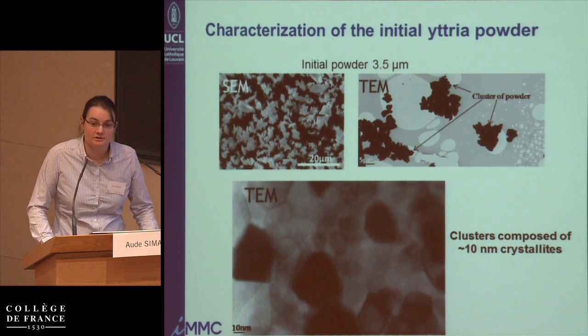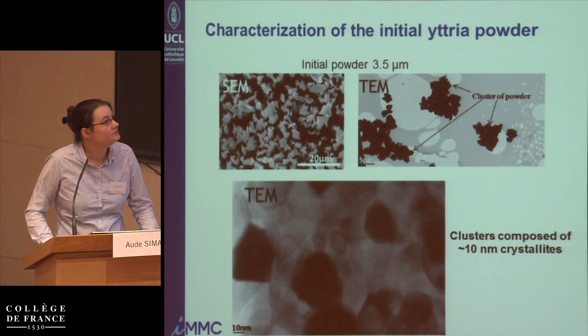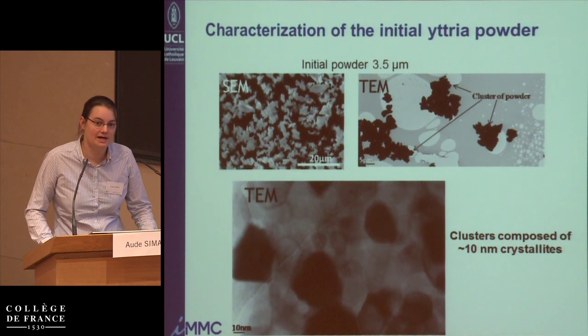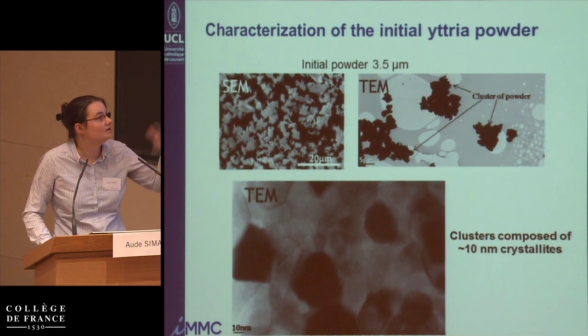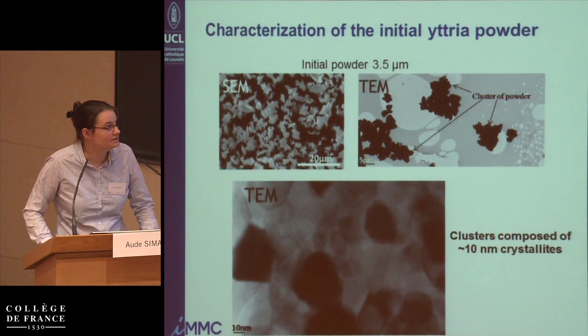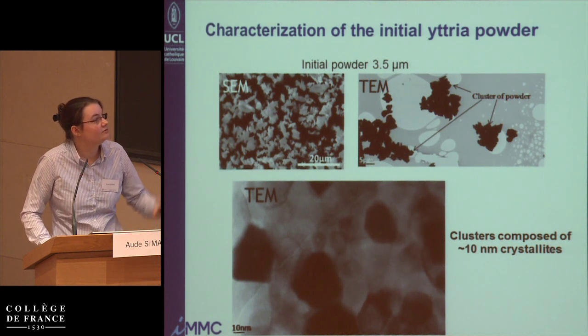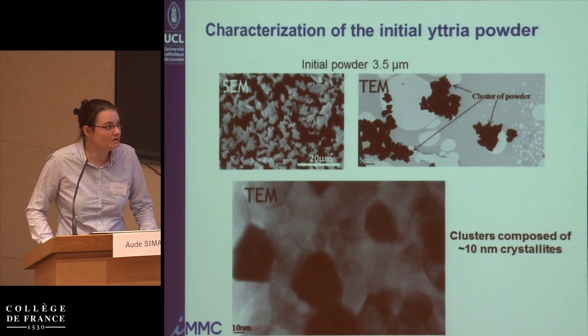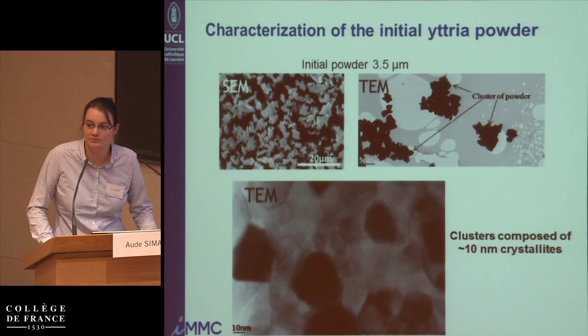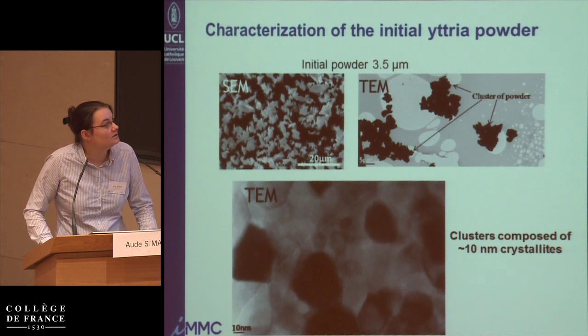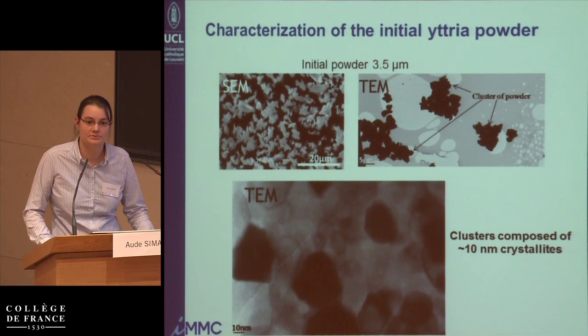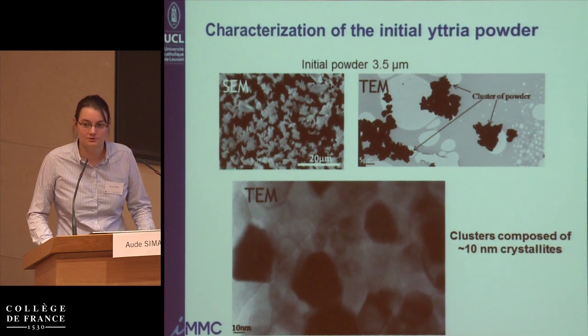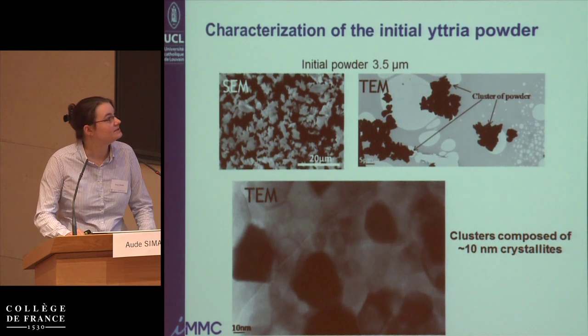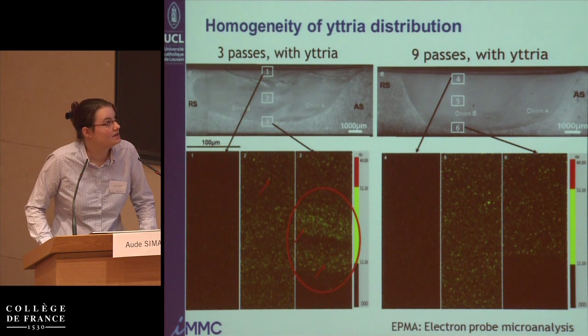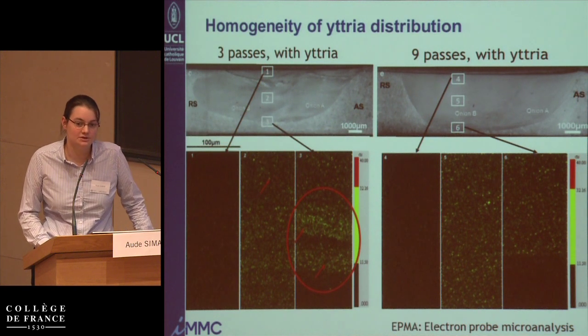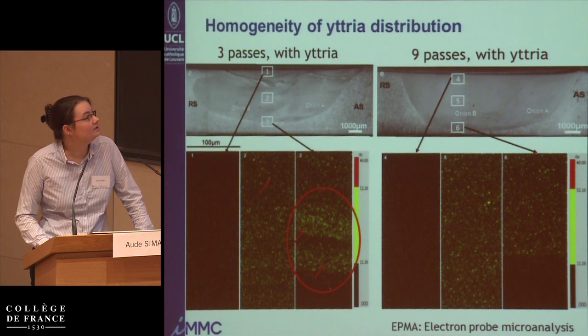So what does the initial powder look like? So the yttria powder is 3.5 micrometers in specific characteristic size. Now it's made of crystallites that are about 10 nanometers in size, and you see that they tend to cluster a little bit together, so that makes it difficult to separate them during the process. So after 3 passes of friction stir processing, it looks like this.